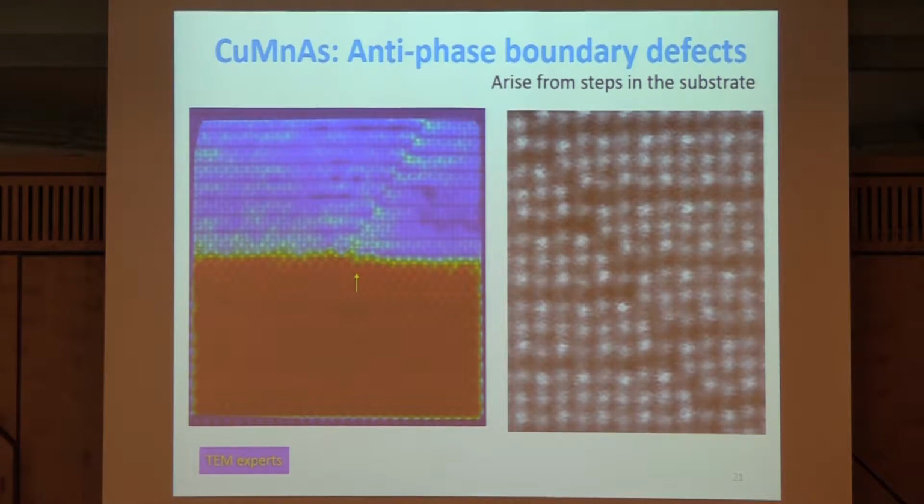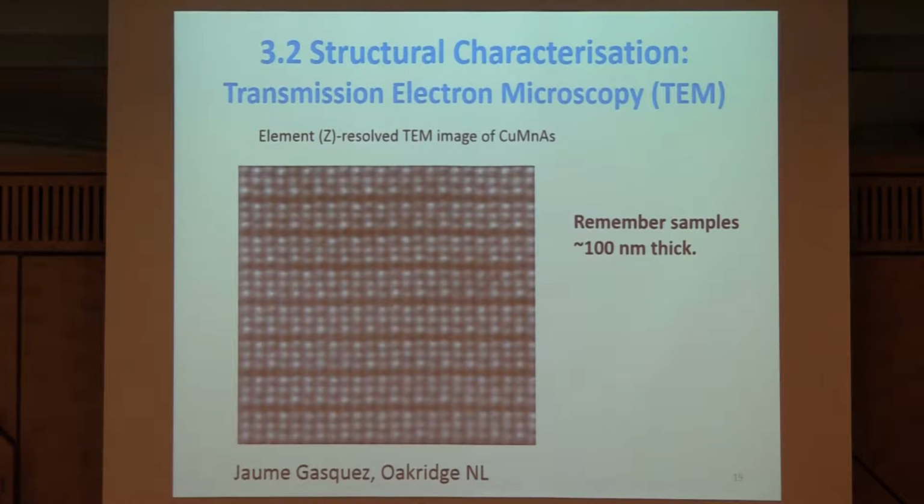But on the other hand, there are some problems you can come into with talking to TEM people. And that is, for instance, when we got this image, we thought, that's fantastic, that's absolutely brilliant. And we didn't think to ask the obvious question, how typical is that? Because, of course, you want to produce a beautiful image, so you look around, this bit's got horrible, this bit's contaminated, this bit's got loads of dislocations, so you don't bother with them, right? So the typical TEM picture is usually the best one we ever produced.